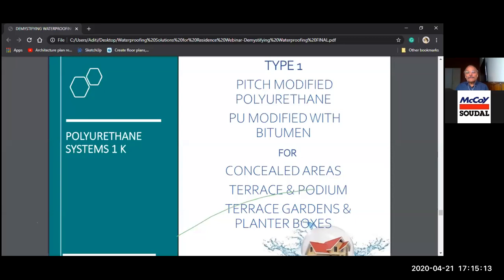So there are two types of systems. Basically, the first type is pitch modified polyurethane, which is PU modified with bitumen, and it is mainly for concealed areas, as it is not UV stabilized. This can't be exposed to sun, and it is good for terrace gardens and podiums. And again, they can be a mix and match of crystalline and pitch modified, or two component cementitious and pitch modified, for terraces and podiums, terrace gardens and planter boxes.